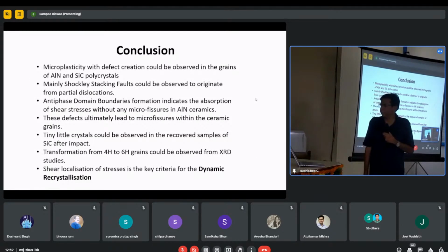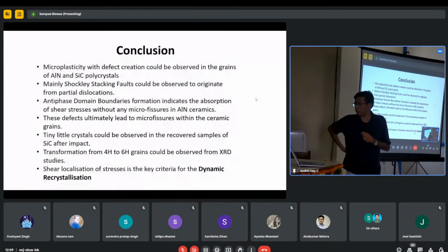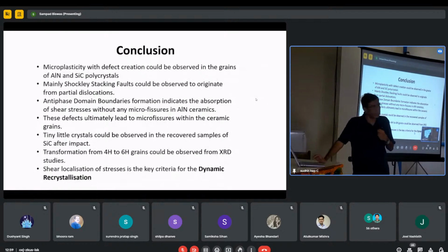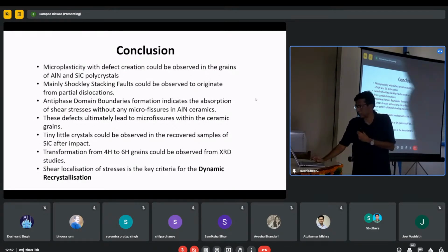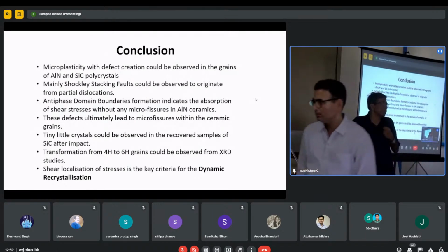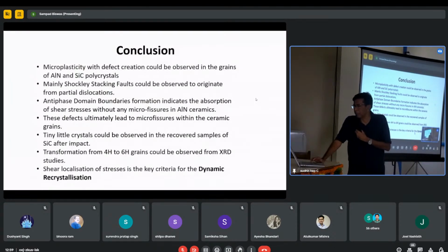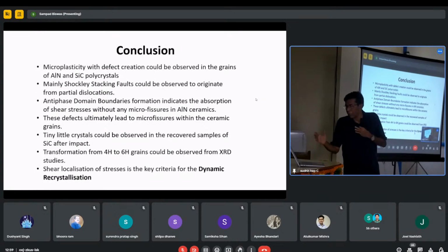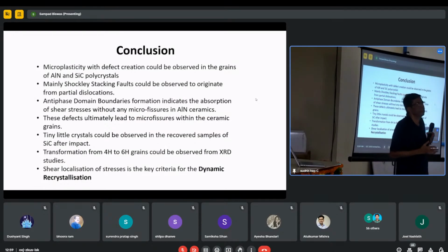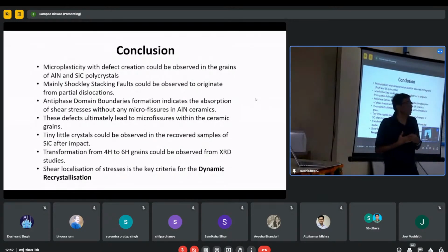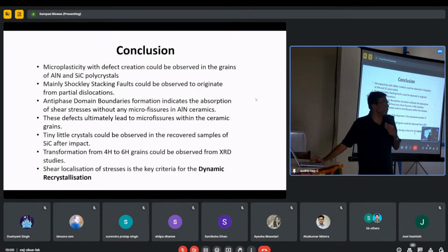So, the conclusion is that microplasticity with defect creation could be observed in the grains of both aluminum nitride and silicon carbide. Mainly Shockley stacking faults we could identify. We didn't find any Frank stacking fault or any other extrinsic faults. Antiphase domain boundaries could also be observed in aluminum nitride. These defects ultimately lead to micro fissures within the ceramic grains. Tiny little crystals could be observed in the recovered samples. So dynamic recrystallization is the main process of microplasticity, and this has never been reported till now. So we are going to communicate it very soon.